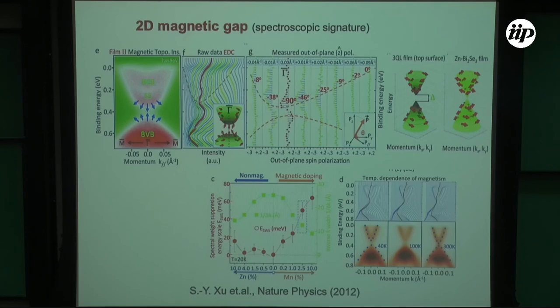Otherwise, how do you explain that in a K-resolved spectroscopy? Because we're seeing that in momentum space. If it were totally disordered or inhomogeneous, then in K space you would see broad features. You should not. The fact that we can resolve these things in K space tells us that there is some degree of homogeneous magnetization in the system. And then we can also see how it disappears as you raise temperature.